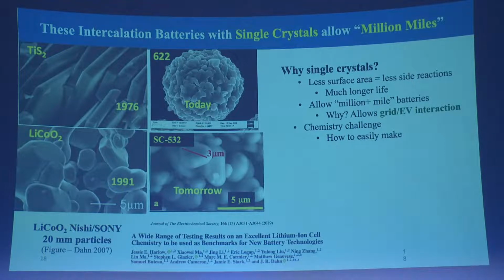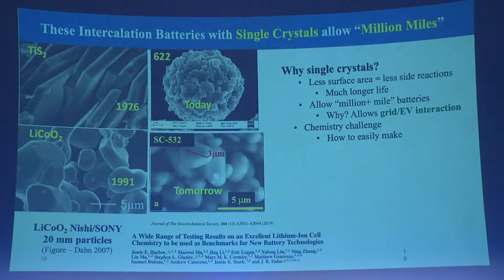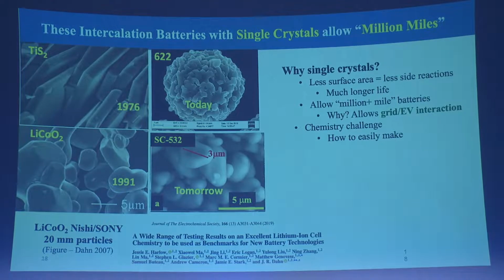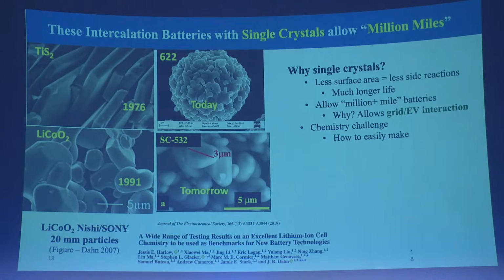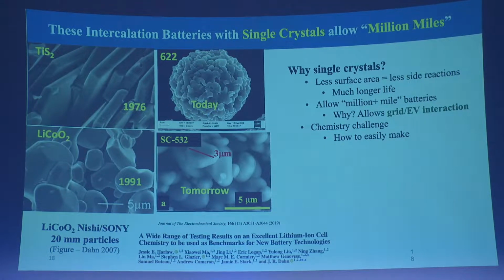So if we go back to square one, back to the 1970s, TiS2, we used these huge crystals. We could make these a centimeter long. Clearly in battery use, we didn't use them that big, but they were hundreds of microns, even for battery use. Sony, when they commercialized lithium cobalt oxide, tried to make the lithium cobalt oxide crystals as large as they could for safety. The less surface area, the less side reactions. Then for energy density, the commercial folks all went to meatballs. And now there's a track back.